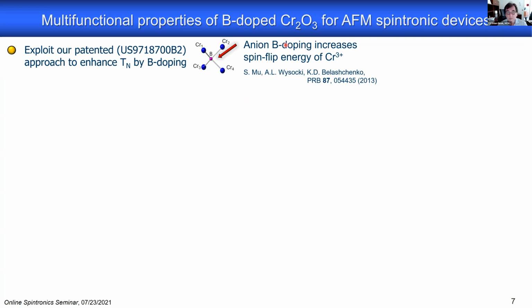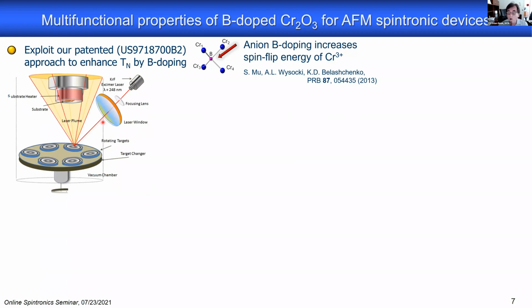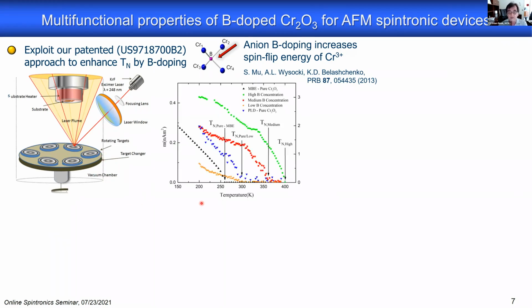And we picked this idea up and asked ourselves, how can we dope? The idea was then to grow these films by pulsed laser deposition in the background of boron, decaborane gas. And we did that, and indeed we created nice films. When you do magnetometry on these films, you can pick up a residual magnetic moment. It's a weak magnetic signal from not 100% compensation, and that moment is directly a proxy for the antiferromagnetic order. By doing so, we could show that indeed, as predicted, we could increase the Néel temperature.